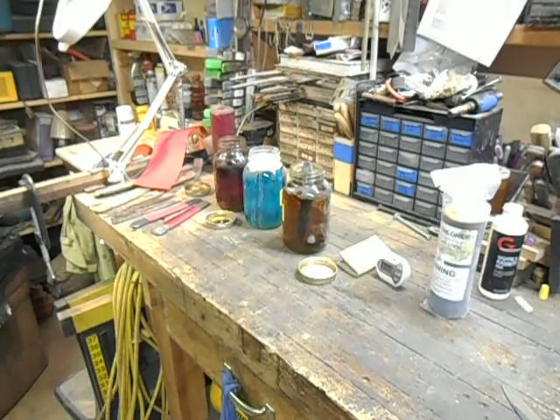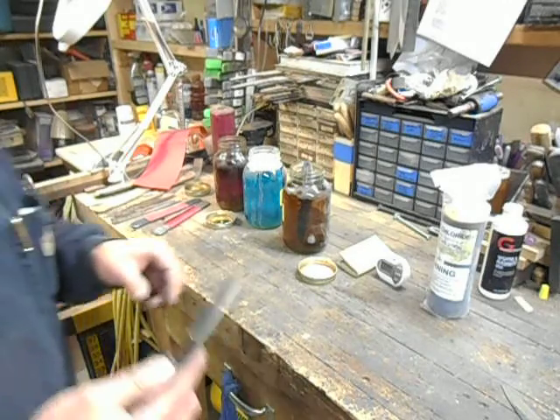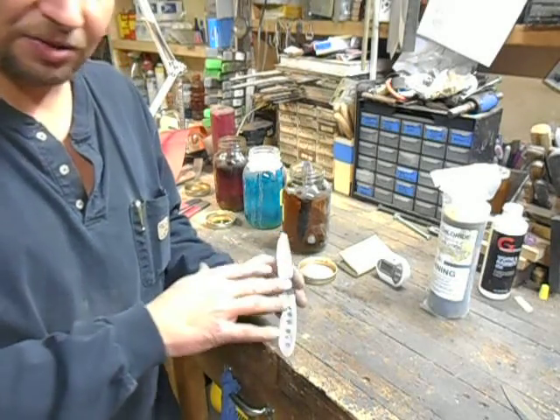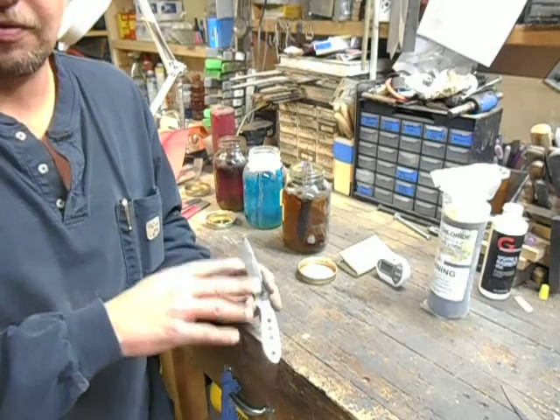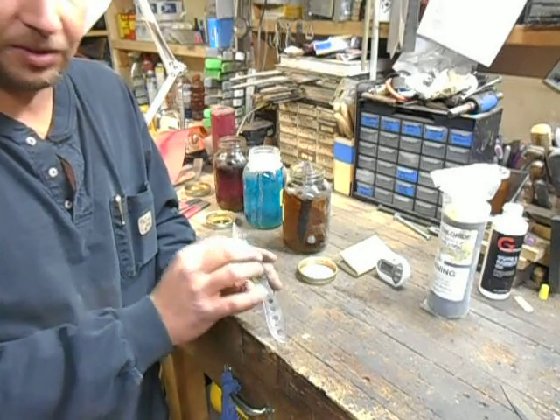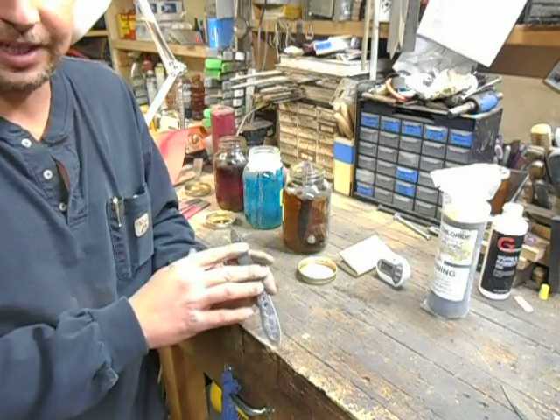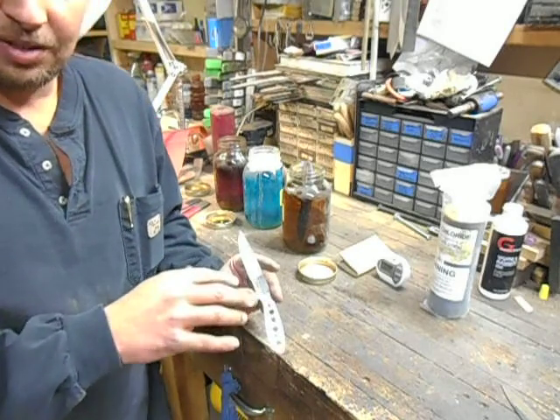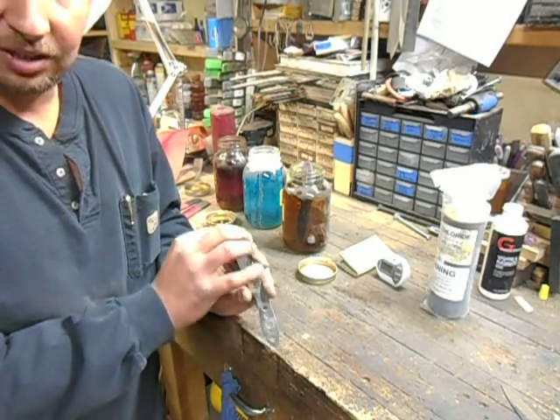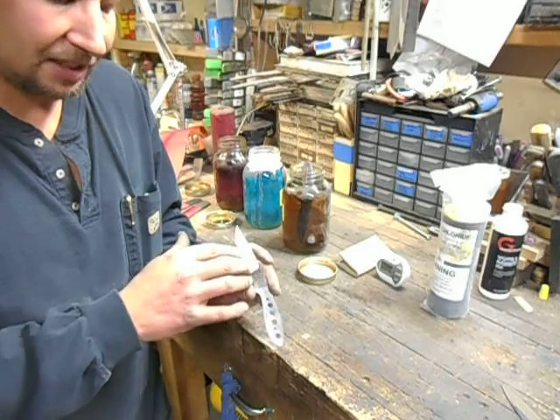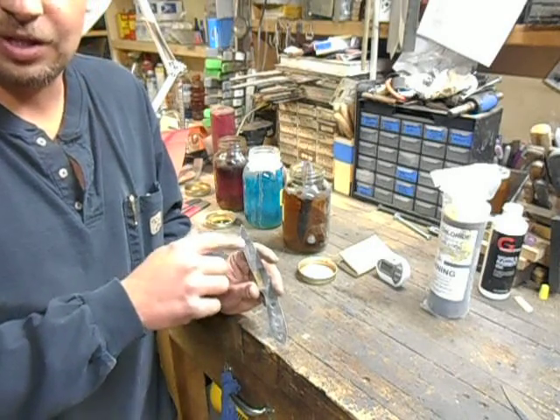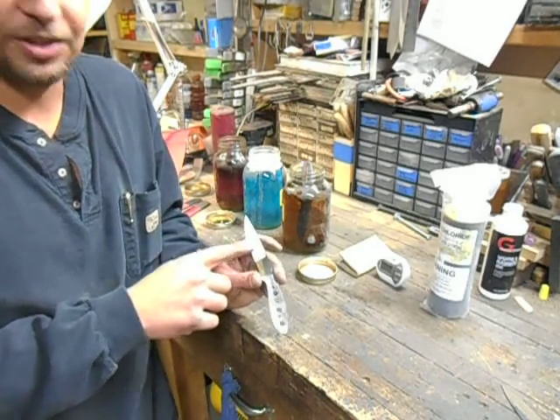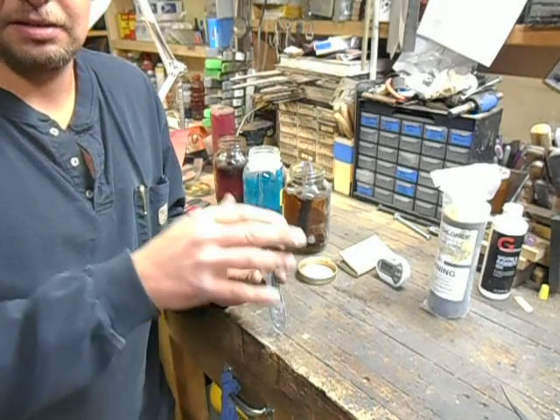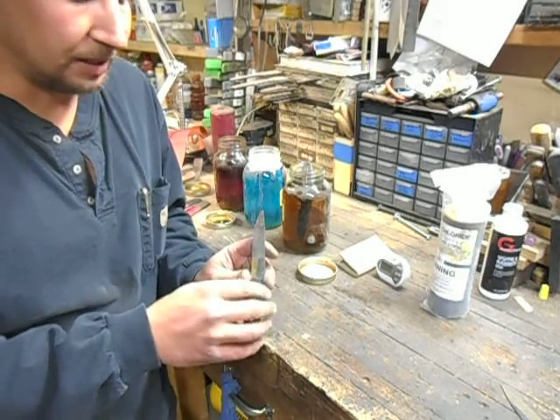Okay, I grind most of my blades, like this one right here, quenched full thickness. There was no bevels ground into the blade before heat treat. The reason I do that is because the steel that surrounds the future cutting edge will protect the steel that's going to be the future cutting edge from the effects of the heat from the heat treating process.